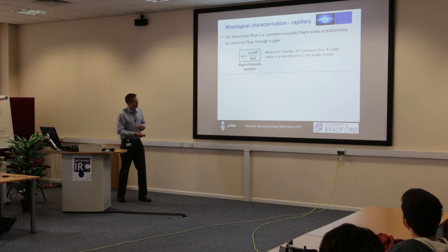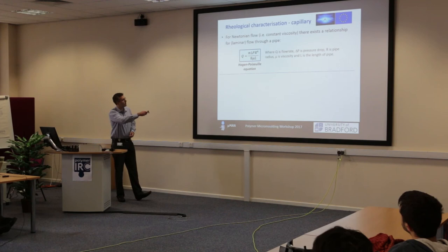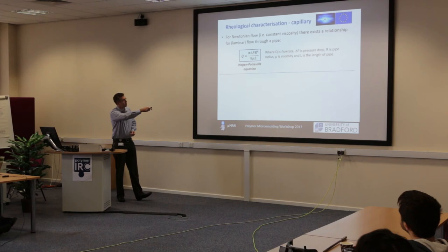So the equations that govern the measurements that we make here are all based on basic Poiseuille flow of a Newtonian fluid, which just tells us that the volumetric flow rate is related to the pressure drop divided by the viscosity. And all these other terms are just the geometry of the channel that the material flows through.